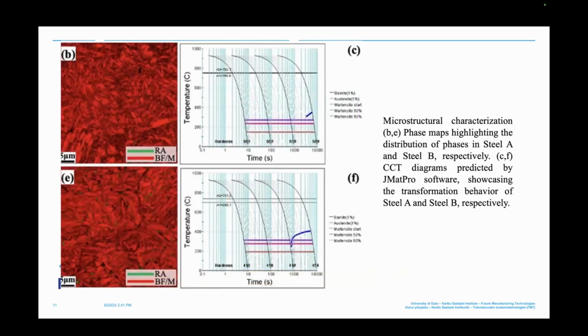Okay, this is also EBSD for both steels after forging and air cooling. We can't identify between ferrite and martensite in the normal EBSD, so we select the BCC index for both steels. So this will be mainly BCC in EBSD, but we have some small green particles, which are retained austenite. Of course, our colleague made color etching to recognize bainite from martensite.